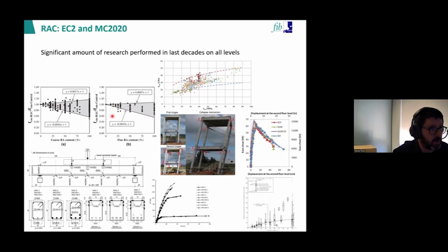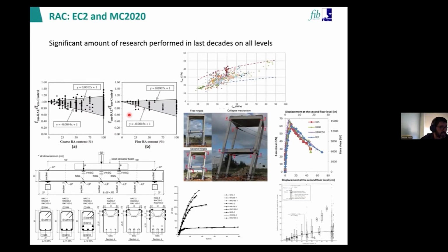The fortunate thing is that when we go to the structural level, this effect is much diminished, because in a lot of ultimate limit states, actually we have the reinforcement which is governing the behavior, right? So in that case, if we achieve basically similar compressive strengths, there will not be almost any difference in structural behavior between natural and recycled aggregate concrete structures. Where there will be is basically in serviceability behavior, because recycled aggregate concrete will have, because of the less stiff aggregate, because of the residual mortar on the aggregate particles, much higher shrinkage, creep, and a lower modulus of elasticity. So if we need to consider deflections, deformations, this is an area where, yes, there are important differences to be considered, right?